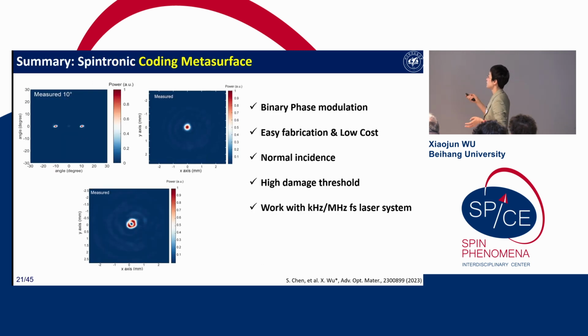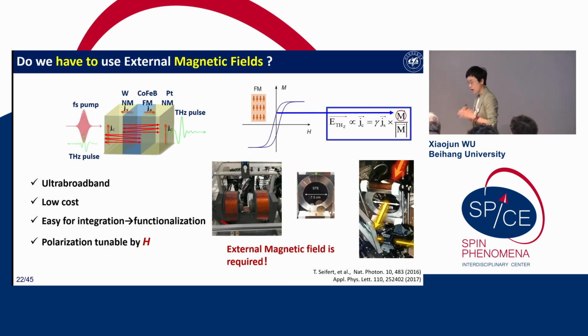So what we just presented is that, since our workshop is on spintronic terahertz devices, we can fabricate this metasurface on the spintronic emitter. We can get many functionalized spintronic terahertz emitters, and this has many advantages. It is low cost, we can coat these metals, and the damage threshold is also high. It can work in the kilohertz and megahertz systems. For the experimental demonstration measurement, we just used kilohertz, but it definitely works in the megahertz system. And for all this work, we have to use an external magnetic field.